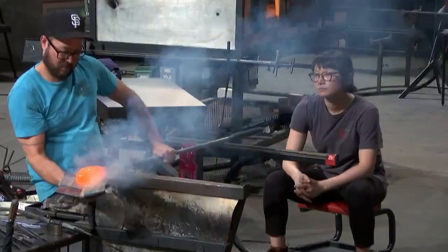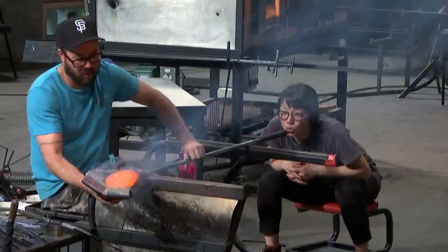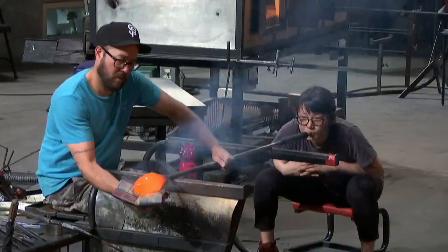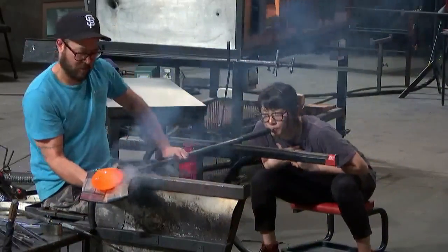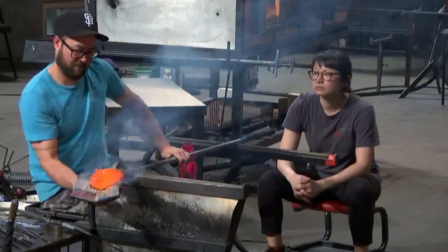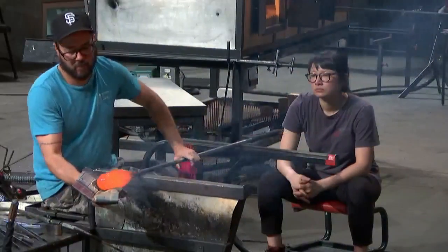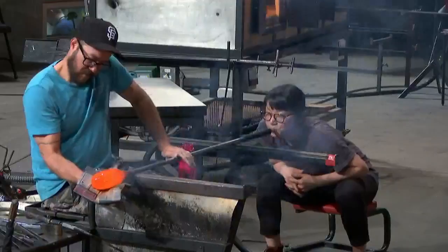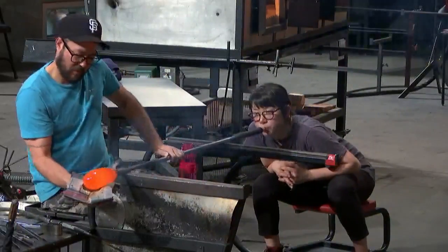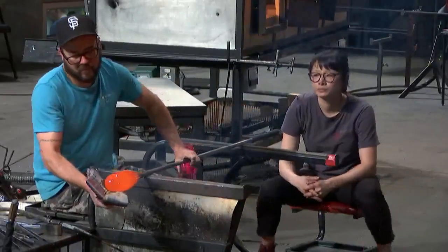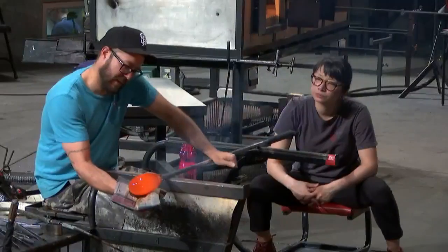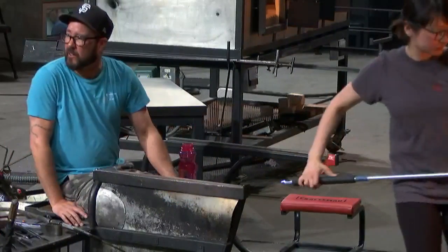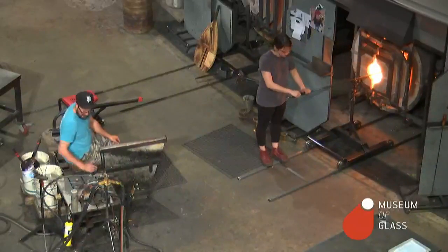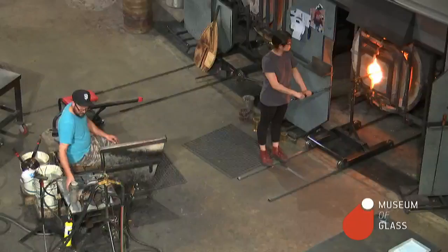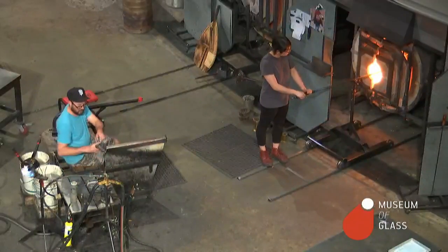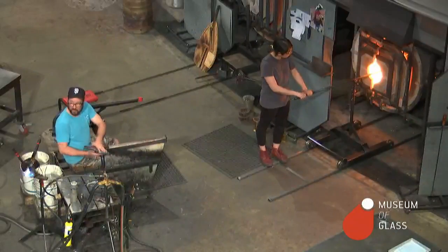We had a guest artist who's a ceramicist, Tamia Tahani, and normally she makes these 3D printed ceramics, and we're trying to combine the ceramics with the glass, and they have two different coefficients of expansion, so the glass cracked. It does look cool, but it wasn't supposed to. You can immerse the glass in water and crack it, but not all the way through. Then you put it back in the fire and heat it up just enough so that the cracked parts stick together.